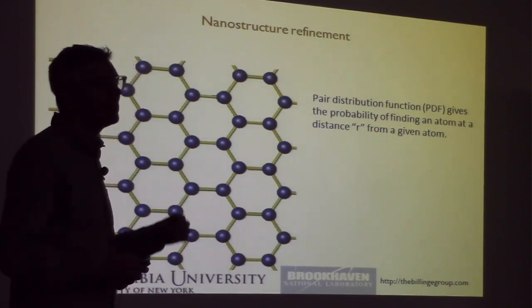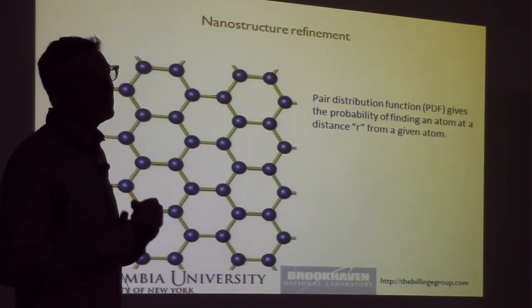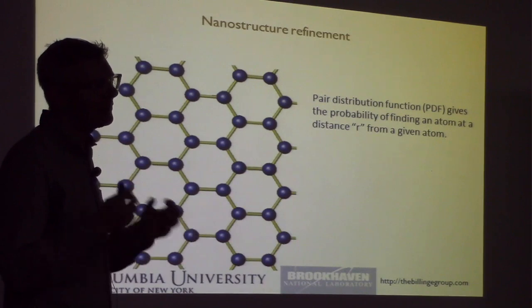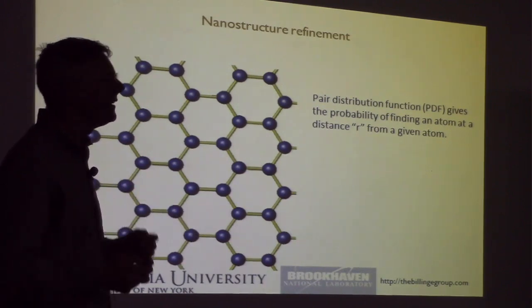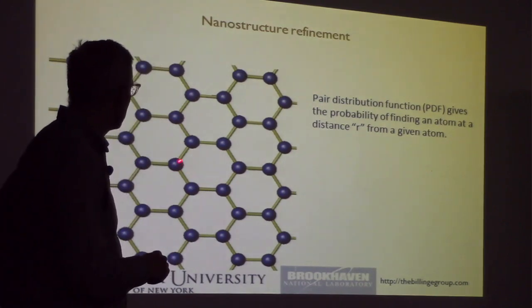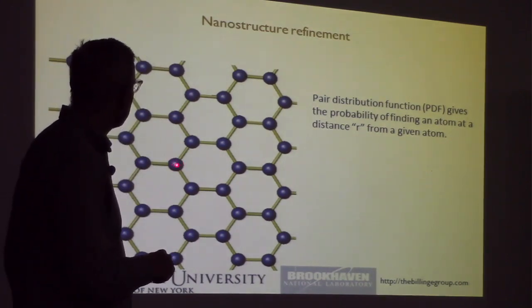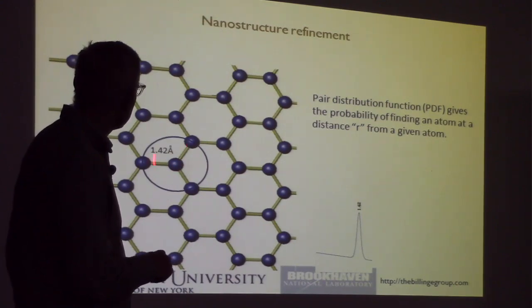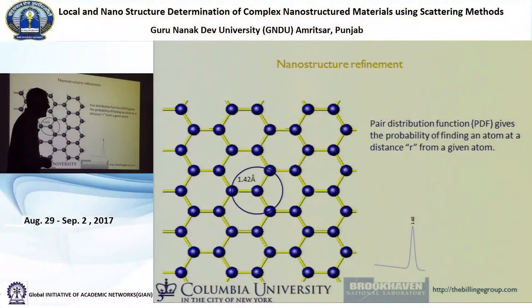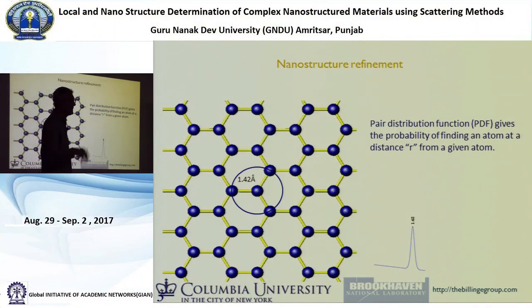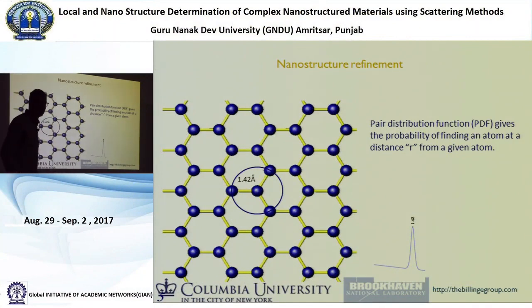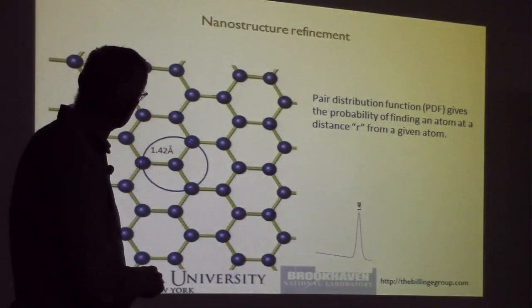So we can get PDF from data. We can also get PDF from model. So if we have a structural model, we can compute the PDF. So you're going to be doing this in your hands-on session. So what we do is we put an atom at the center, and then you go out some distance until you find another atom. So this is graphene. Graphene is really hot right now, so you have to have graphene in your talk to be taken seriously as a scientist. Right? So here's my graphene.